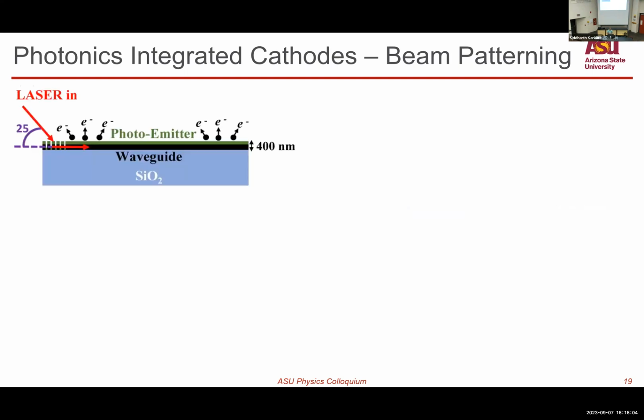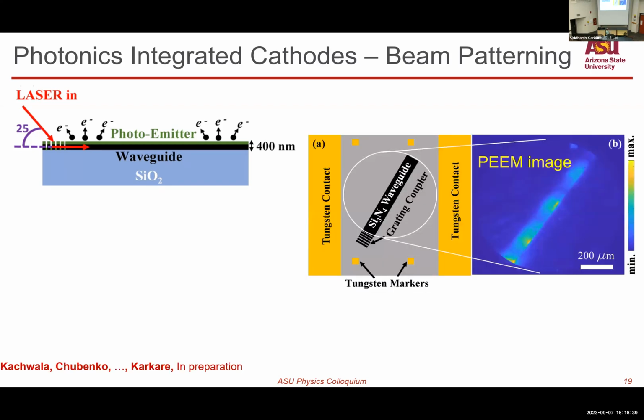The other approach for getting a transversely patterned electron beam is using photonics integrated into the substrate of the cathode. We were able to develop a device where we had a silicon dioxide substrate with a small 400 nanometer waveguide of silicon nitride on top of it. And we deposited a thin film of alkali antimonide, cesium antimonide on top. And there was a grating coupler in this waveguide, which coupled the laser into the waveguide. And as the laser traverses through the waveguide, it excites electrons from the surface. And basically, we see the same pattern of the waveguide in the electron beam image. And we were able to measure this image, and you see the electron emission is largely confined to this waveguide.